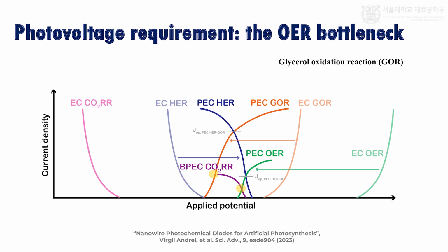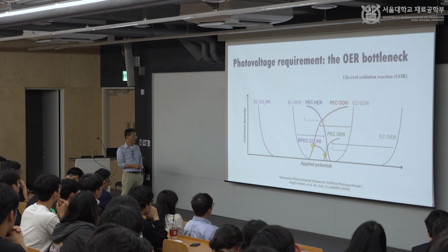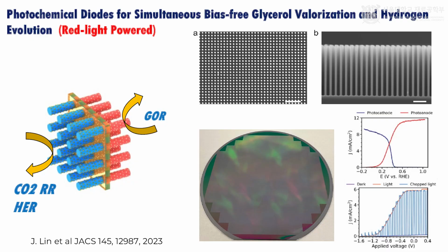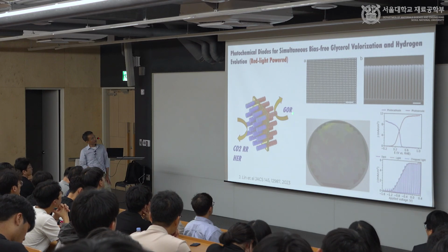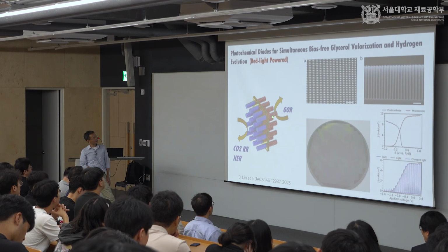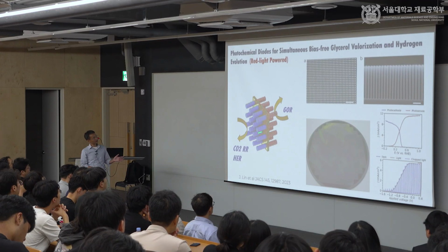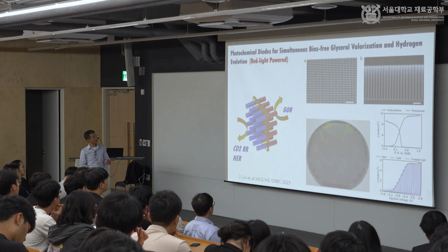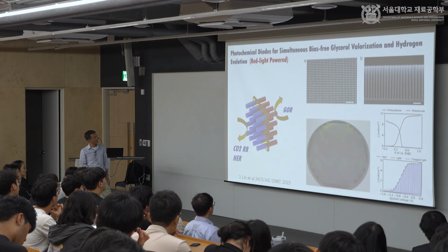On the OER side, we know the titanium oxide absorption is low, so the photocurrent is always low, limiting the silicon photocathode performance. Basically, this is just an illustration. We can do HER, we can do CO2 reduction. The most important thing is that when you start to remove OER from the anode side, the photocathode can be silicon and the photoanode can also be silicon. Because with silicon, you can very easily do larger scale processing, 6-inch wafer or 12-inch wafer.